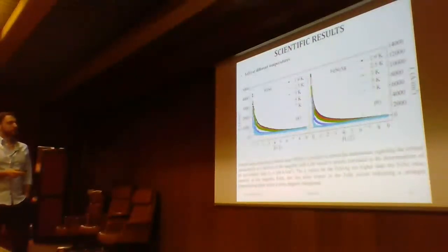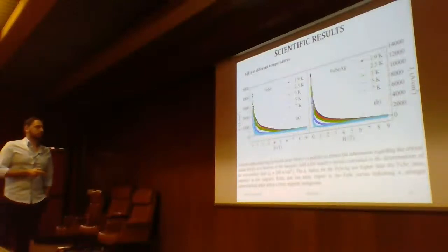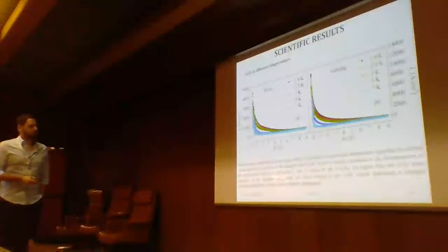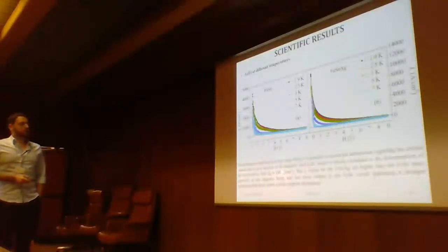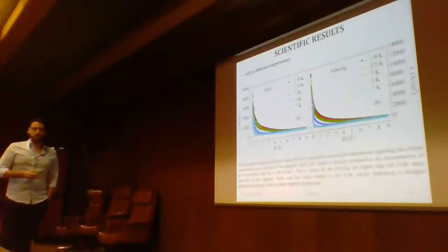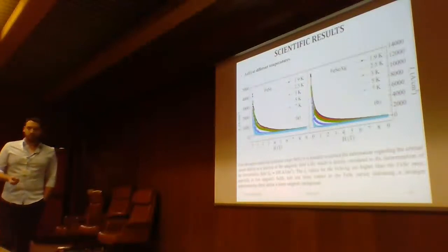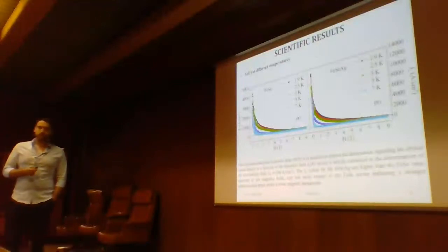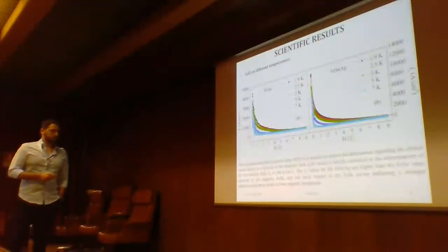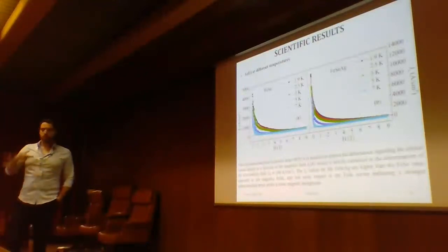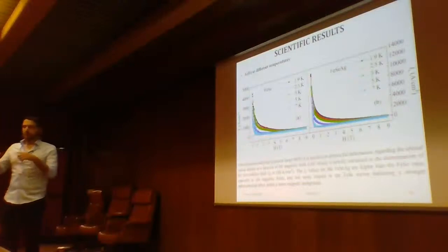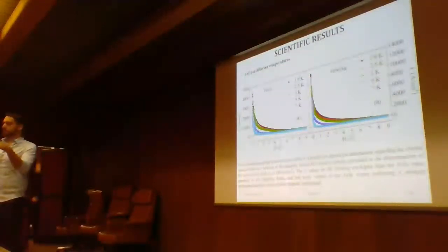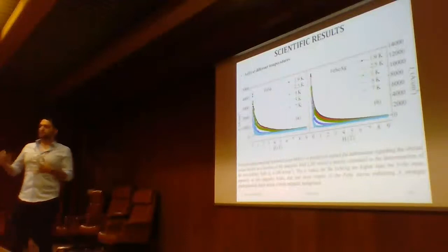In particular, from this critical current density, you can also extract the so-called irreversibility field, using the criterion of taking Jc equal to 100 ampere per centimeter square. Now, what is the irreversibility field? It is a very important characteristic of superconductors because it is the particular field above which vortices are free to move inside your sample. So the pinning is equal to 0.